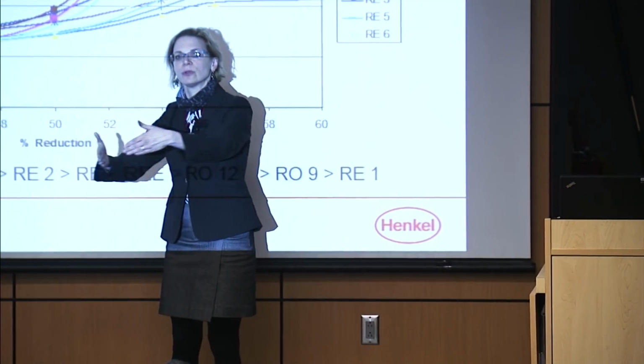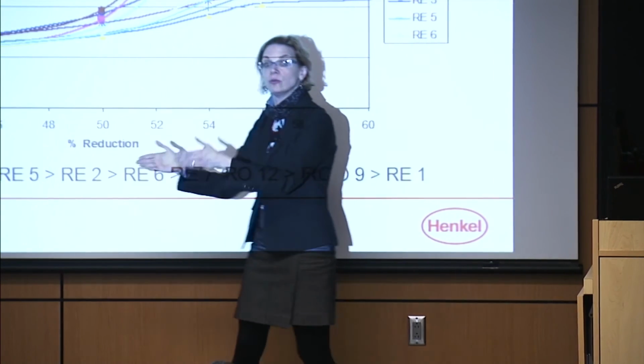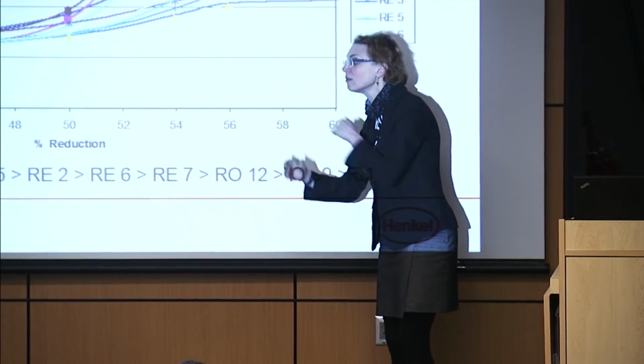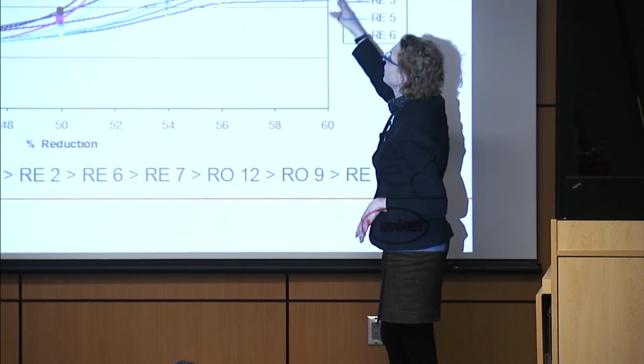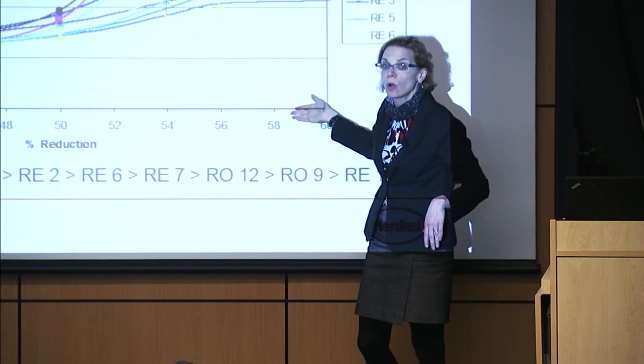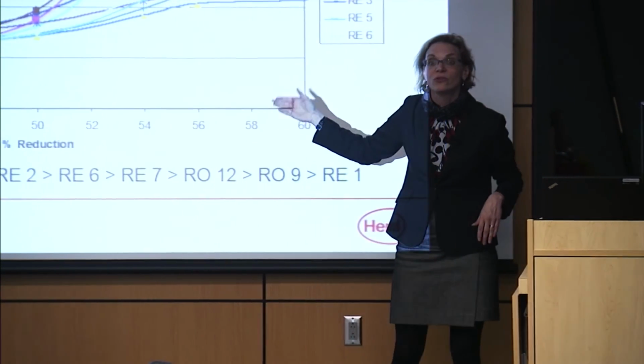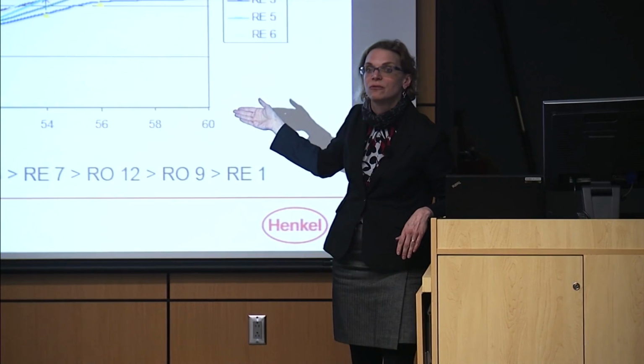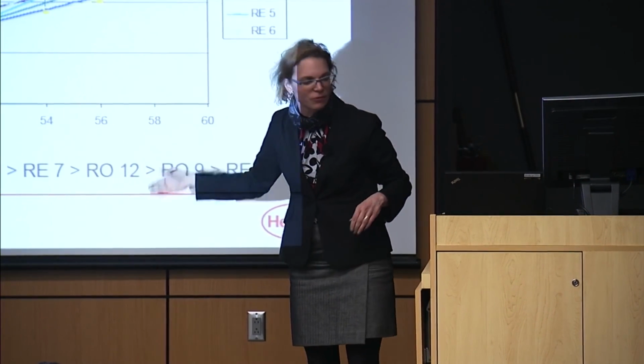50% is basically we've reduced the strip thickness in half in one pass, so through one pair of rolls. We want to be able to do that at very high speeds and very low roll force. This roll force is very critical. That's what we're shooting for. We're shooting for that big reduction and that low roll force.